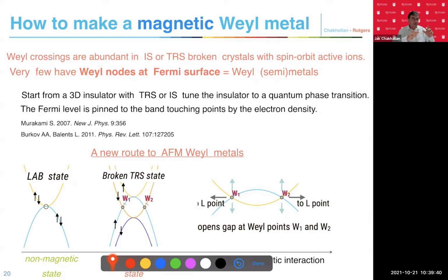But if you could somehow dynamically, for example by using light or microwaves, introduce spin fluctuations and reduce the value of the magnetism, then you could still push them back into the Brillouin zone, and you would have many more dynamically generated Weyl crystals. It's just an idea. A German theory group from Dresden actually has a wonderful Nature Communications paper on how to do it with light: they apply light to fluctuate the spin. So yes, you're correct. It survives because the paramagnetic state is kind of unique. But otherwise, you're correct. I see. Okay. Thank you.